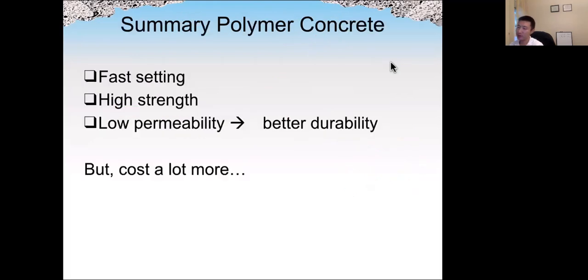All right. So in summary, we discussed three types of polymer concrete. They are polymer concrete, which uses polymer as the only binding agent. And then we discussed latex modified concrete, in which latex is basically a chemical admixture in normal concrete. And then we discussed polymer impregnated concrete, which is a treatment of traditional concrete after the concrete hardens. We use monomer to penetrate the concrete and then polymerize the monomer to seal the cracks and the pores.